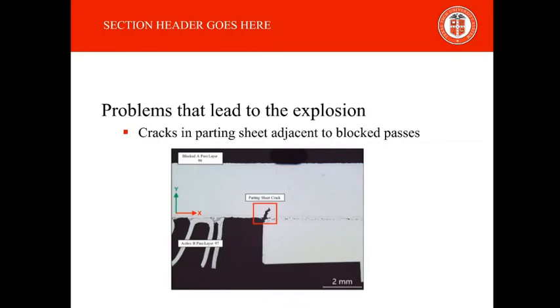Assuming this crack extended through the layer, it would have allowed fluids from the active pass to the blocked off layers. This crack could have been present at the time of the 2015 repair, since no evidence is shown that they performed a leak test, or the crack could have developed in the 205 days of operation after this repair. The crack in the parting sheet adjacent to the blocked layers is the fourth and final step necessary to create the catastrophic rupture that happened on June 27th.